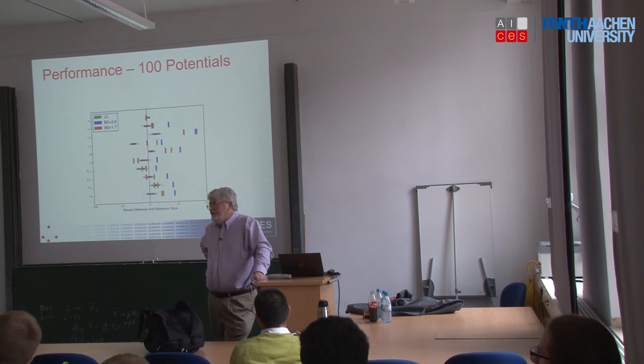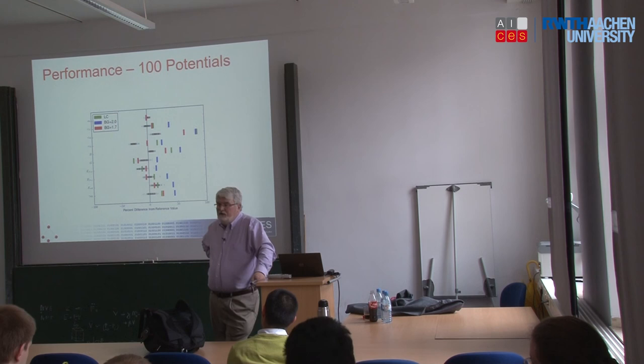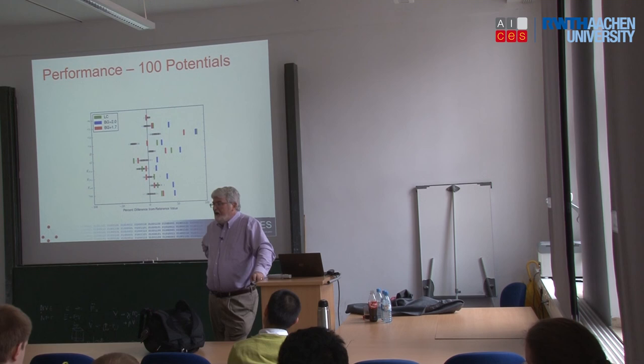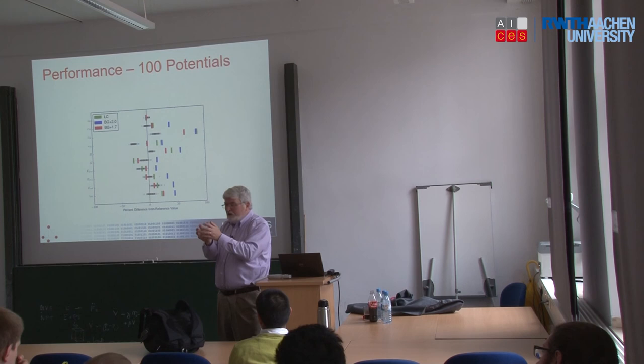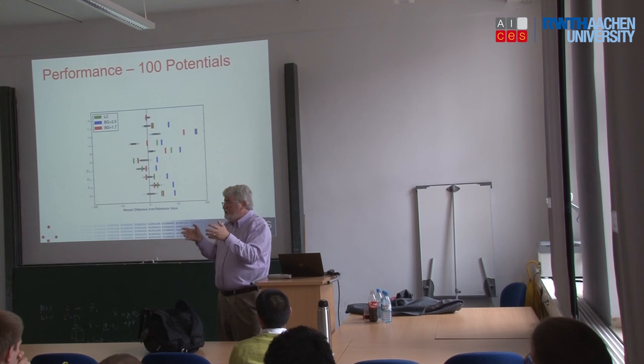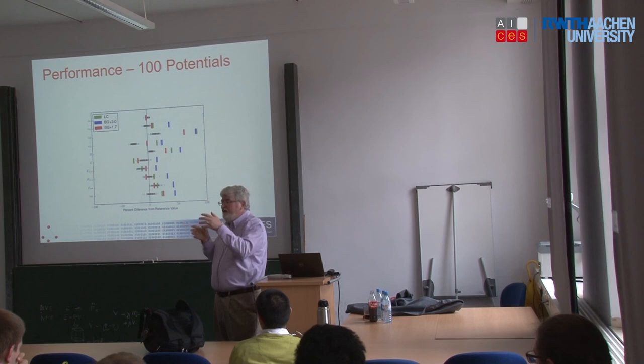We've talked about that. You're not going to be able to do that on the fly. For these sort of dynamical quantities, you're going to have to find some surrogate quantity which is easy to calculate and which at least captures something. So you might calculate a Grüneisen parameter, for example. For the melting point, you can't compute it directly, but you could look at the energy of the system against a large volume excursion, not just the elastic constants, which probe 0.1%, but 2%. That's roughly the volume change at melting, I think. So you could look at the volume at melting, and that means you're going to capture some aspect of that curvature correctly.